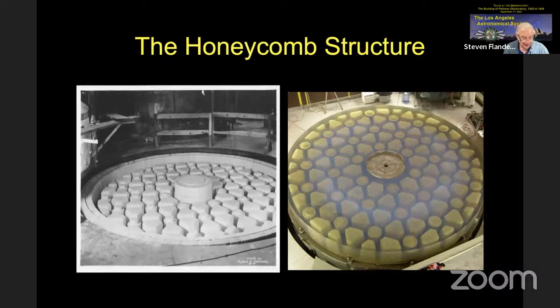The cores, in fact, displaced more than 18 tons of glass. This weight reduction was essential because the telescope's mounting could not have supported the weight of a solid block of glass. And since no part of the structure is more than 5 inches thick, the voids allow air to circulate so that the mirror reaches ambient temperature more quickly. And finally, this structure actually increases the mirror's rigidity.